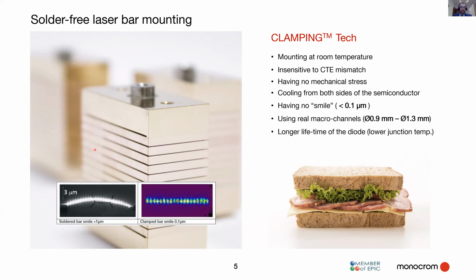Another effect is that due to the clamping, we do not have any smile. Showing an example on the lower left section of the slide, the left picture illustrates a soldered bar where you can see that the emitters are having a bowing. Due to the cooling down procedure in soldering processes, you have a mismatch in the thermal expansion coefficients, which leads, unfortunately, to this kind of effect.